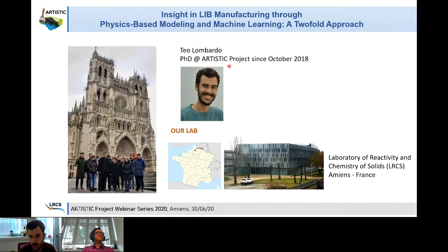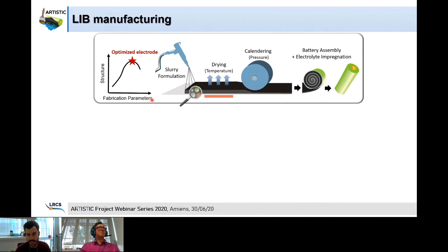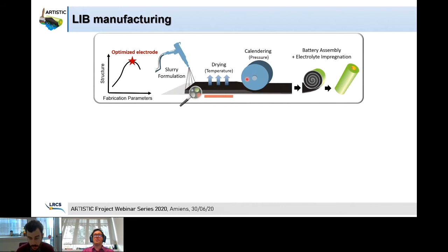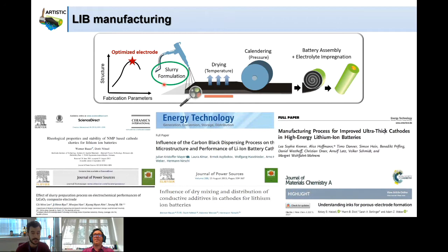We will get insights into lithium battery manufacturing, focusing mainly on one step of manufacturing. In general, manufacturing is a complex process that relies on different procedures. We start with our components — the active material, conductive additive, binder, and solvent. We mix them to obtain a slurry, coat it on a current collector, dry it in an oven to remove the solvent, and obtain a dried electrode that can be further compressed through calendering to achieve lower porosity.